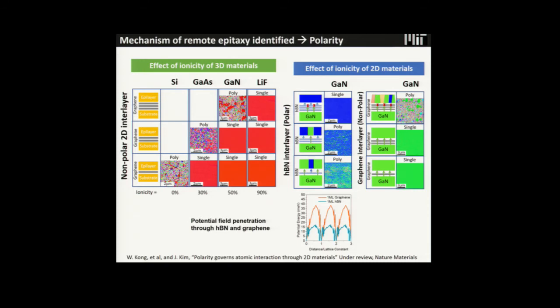If you go through tri-layer, you get the poly. Lithium fluoride is interesting. Lithium fluoride, 90% ionicity, up to 3 layers of graphene, you still get the single crystalline. So we have strong evidence that this is all because of the ionicity of the involved three-dimensional material.